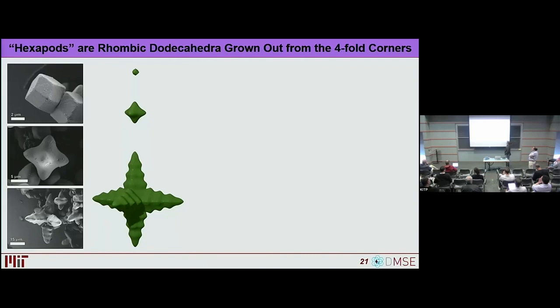We think this is indeed a kinetic structure. Essentially what's going on is that as you cool more slowly, you have more time to grow to a bigger crystal, but there's also a double-edged sword, in that you're decreasing the energy difference between a stellated structure and a perfect Wulff polyhedron. So yes, you have more time to get there, but it takes even more time to actually reach that state. So if we were to do what you're suggesting, we would probably backfill to that.